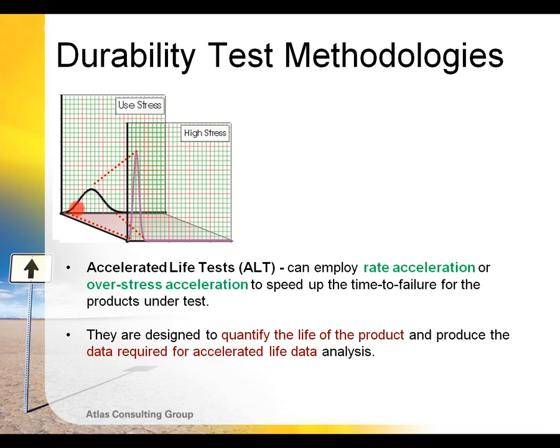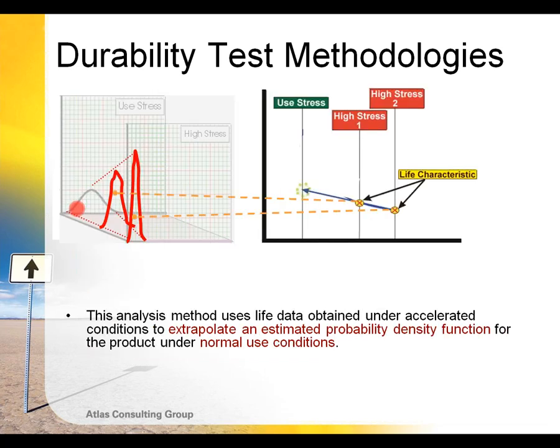So it's important to realize that in accelerated testing, we really typically only have two possibilities for acceleration. One is what we call time compression, where we simply shorten the test cycle. In the case of cyclic fatigue types of failures, like a door hinge, instead of opening a car door twice a day over a period of 5 years, I can do maybe 10,000 opening and closing cycles in a 1 week time period with a robotic arm. So we have time compression, and then we have overstress, where we are using higher than normal stress levels to try to estimate the service use stress levels delivered over a longer period of time.